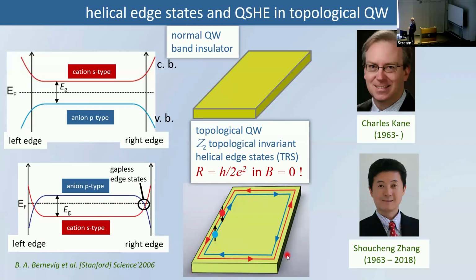But now, since you are in zero magnetic field, the states must be doubly degenerate because, of course, Kramers' theorem works. So you have two states which are connected by the time reversal symmetry operator, and therefore you have a helical situation, not a chiral situation, but a helical situation. Electrons go here in one direction, and another electron, as required by time reversal symmetry, is going in the opposite direction, and the spin of this electron is opposite to the spin of that electron. And you expect a quantized value in zero magnetic field, which is now h/2e^2, because you have these two helical states on both sides. And what about experiment?